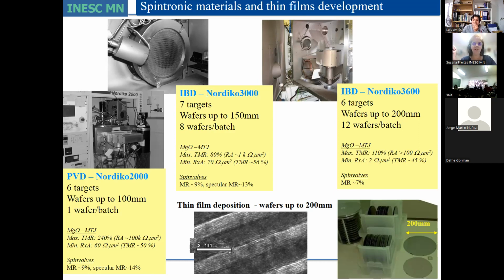In order to do that, the cheaper way is to process a wafer with the sensors all oriented in the same direction, all of them. And then with a laser and a small magnetic field, you go on top of the sensors in the area of the wafer you want. You hit with a laser, and then simultaneously you repin with a magnetic field that sets the 180-degree orientation for that particular sensor. So this laser repinning is a very widely used strategy for industrial partners in 8-inch wafers, wafers with more than 60,000 sensors. They should do this to half of the sensors, so it takes a few hours, as you can imagine.